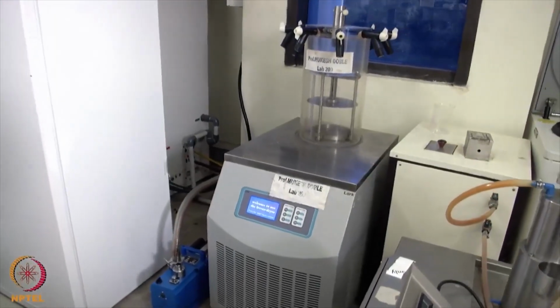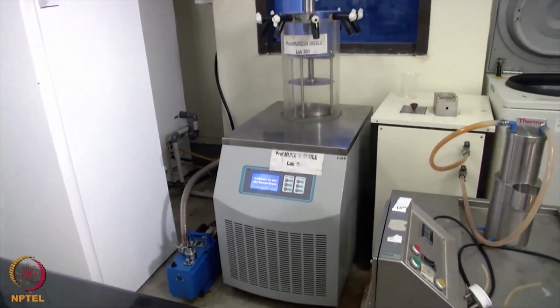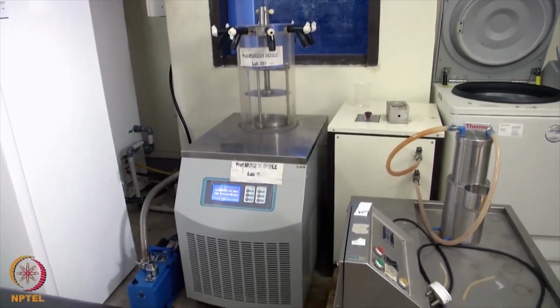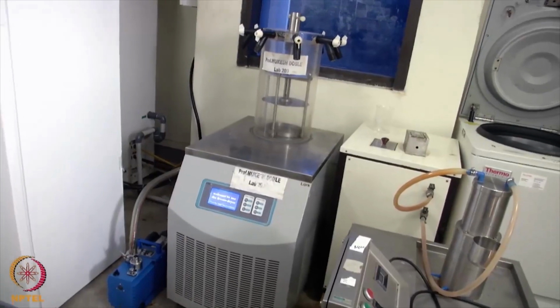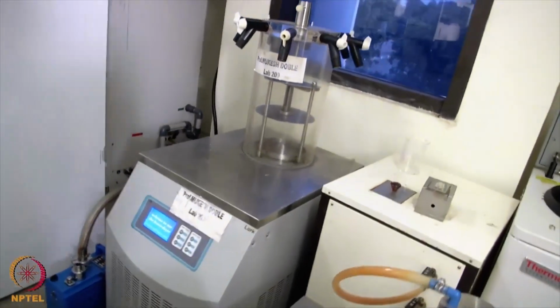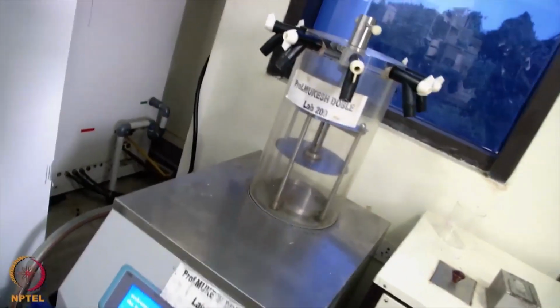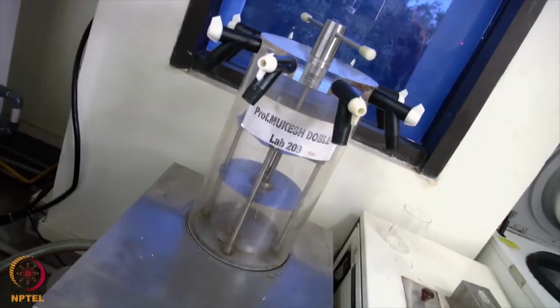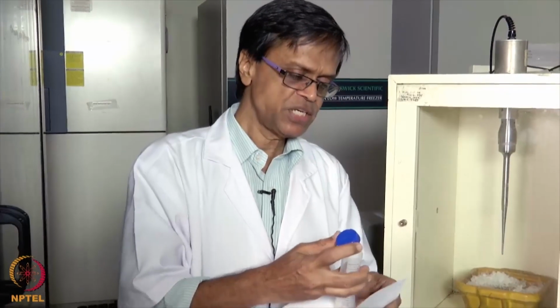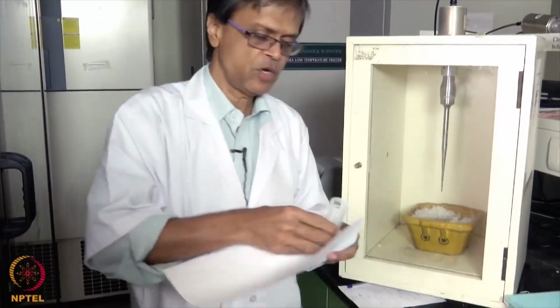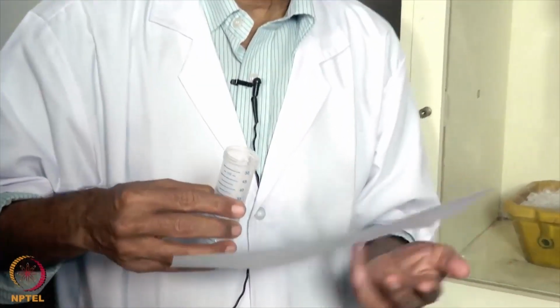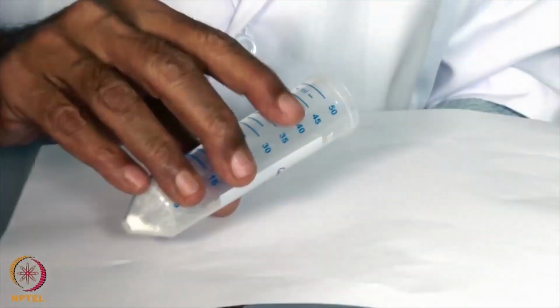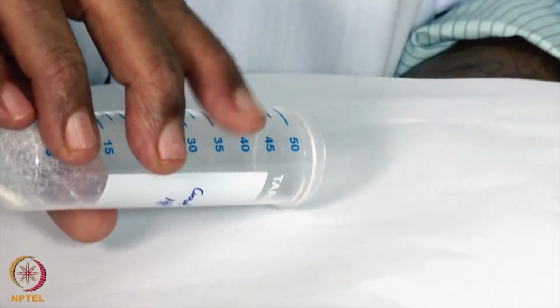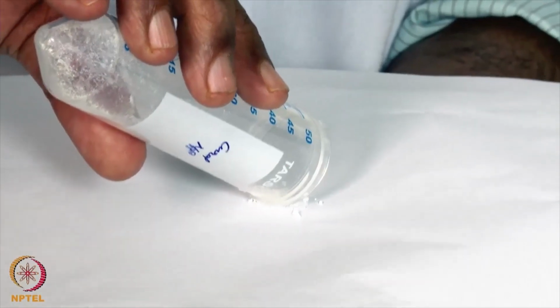This is a lyophilizer where the wet nanoparticles can be completely dried by removing the moisture at about minus 80 degrees centigrade, and this is run overnight so that all the water gets removed. After centrifugation and lyophilization, we get a dried nanoparticle of beta glucan or curdlan stabilized by polyvinyl alcohol.